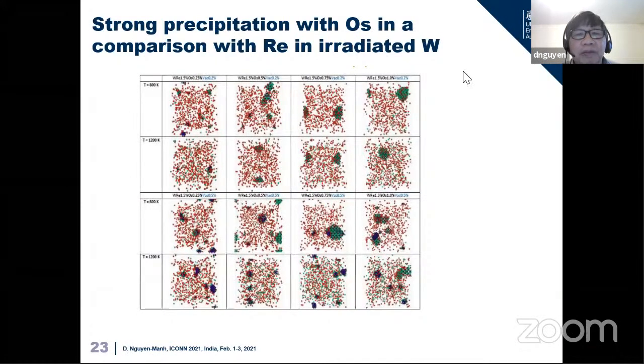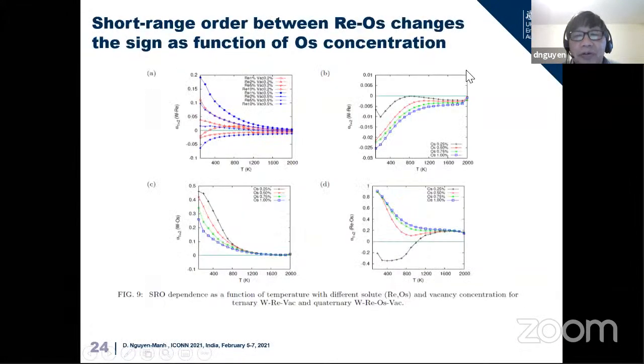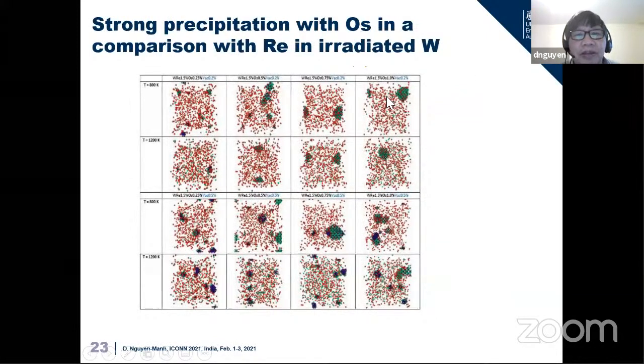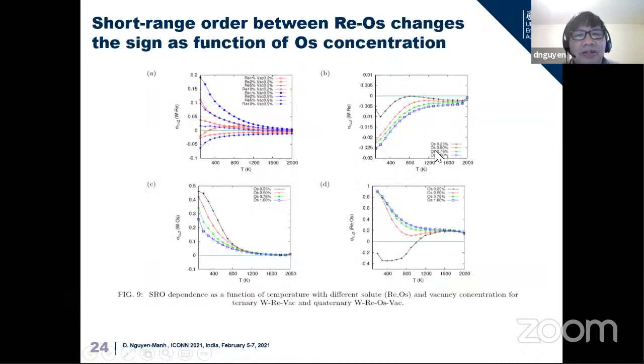If we have osmium coming in, because I have only a few minutes, I can only go quickly. But the key thing is that if you have rhenium together with osmium, then osmium, even at very low concentration, is dominating in void decoration, as you see green here. What you see here is very sensitive to osmium concentration. We see the short-range order between osmium and rhenium changing sign from positive to negative, from high concentration of osmium to low concentration of osmium. When it's negative, it means that rhenium and osmium can be correlated inside or precipitate together.